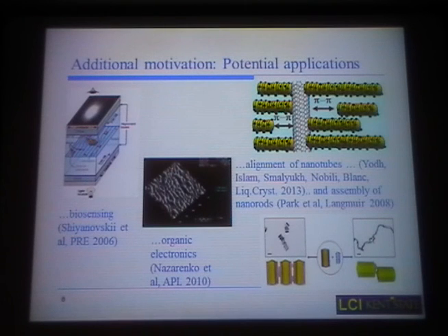And could you control the degree of concatenation? I mean, you know, 10 rods, something. Well, that is harder. We had it with the pH. If you change the pH, the chromonic aggregates disintegrate or assemble again. And by controlling pH, we were able to control the aggregation number of the gold particles.